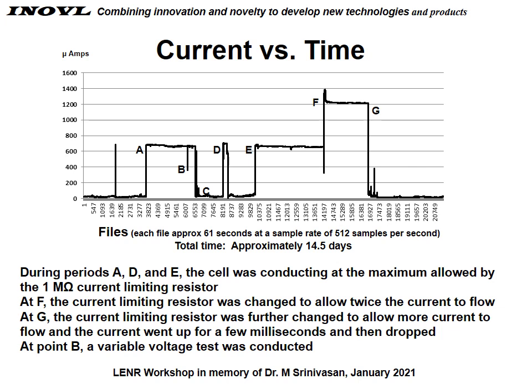At point E, it went back up and stayed up for a day and a half or 2 days, at which point we realized that the current limiting resistor that we had in the circuit was limiting the maximum amount of current that we could measure through the cell. So we changed the electronics, changed the resistance so that we could conduct twice the current. And when we did that at point F, it jumped up to over 1200 microamps. We thought it lasted there for a day or two.